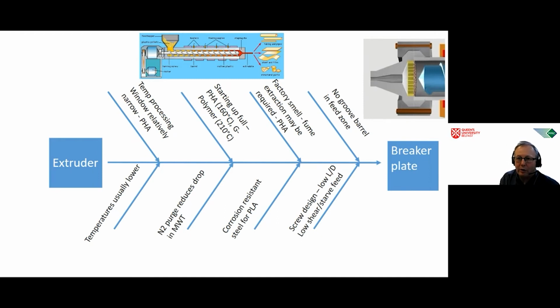So if we just move on now to how will these materials perform during the extrusion process? The most common observation really is that most bioplastics are processed at lower temperatures than conventional materials, usually less than 200 degrees C, and almost all have a narrow processing window, but this is particularly evident with PHA,